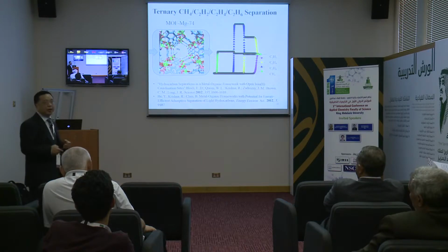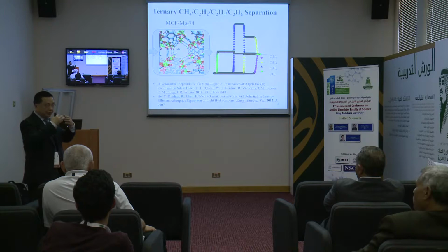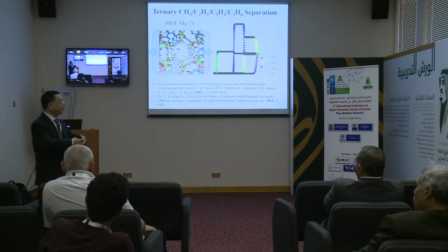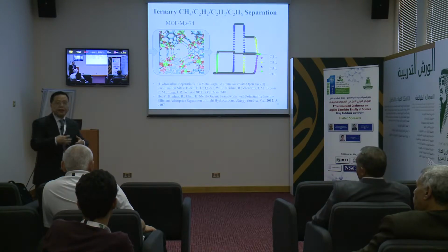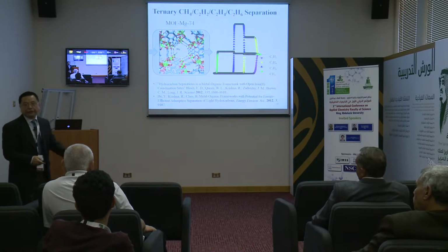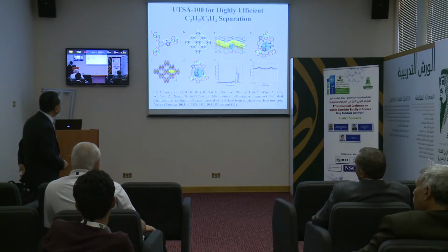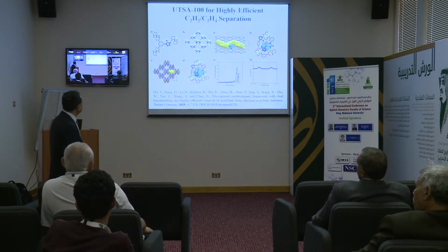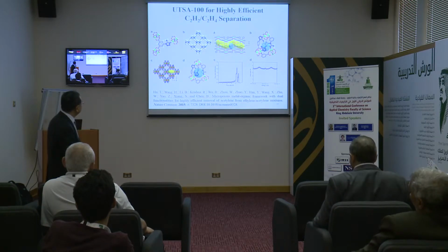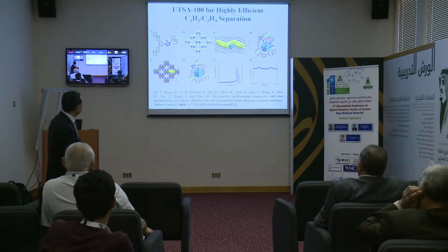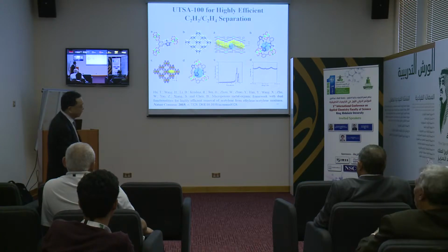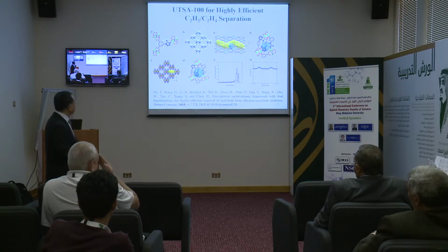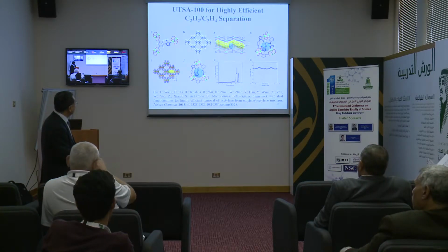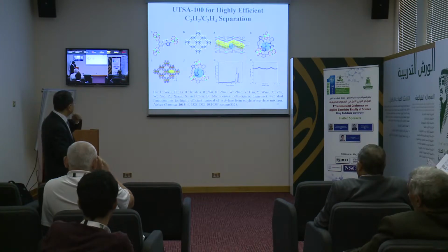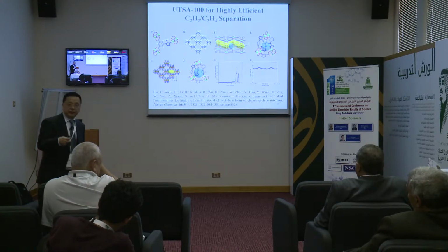So the ideal one is a MOF material that can take up a large amount of acetylene and also has high selectivity. This is the best one for the separations. So we realize this is a unique example of a MOF material. This MOF material has a quite unique pore, about 4 angstrom, so the selectivity is quite good. Furthermore, some of these small cages are useful because they can only take up acetylene.